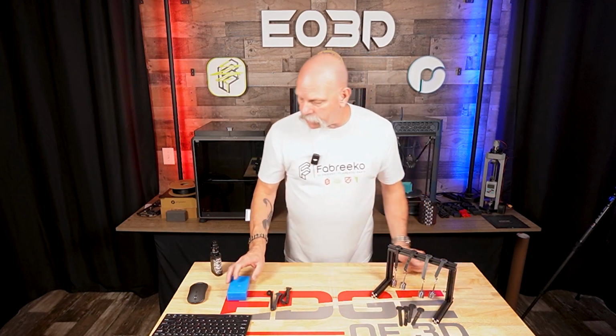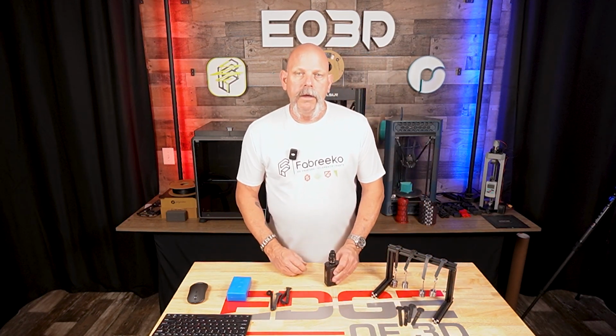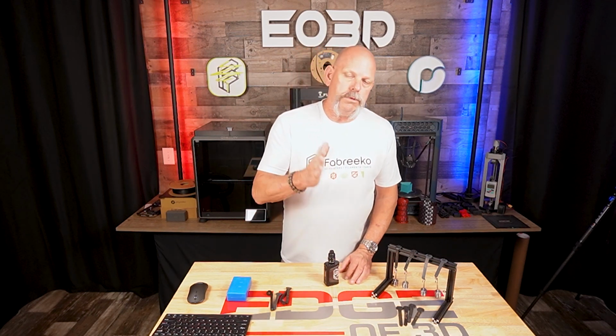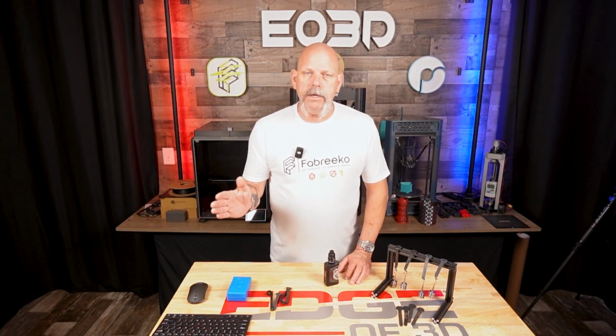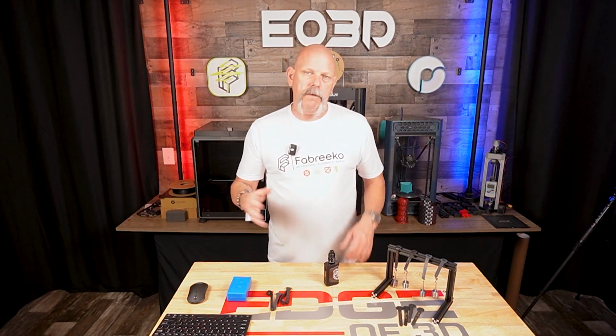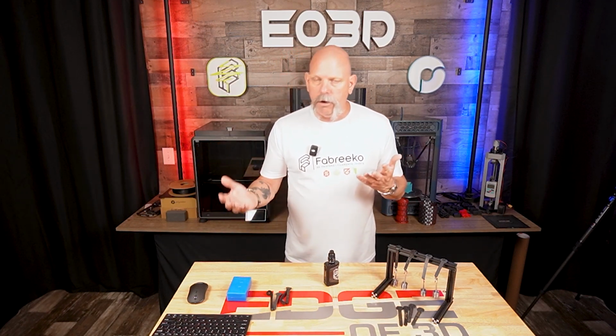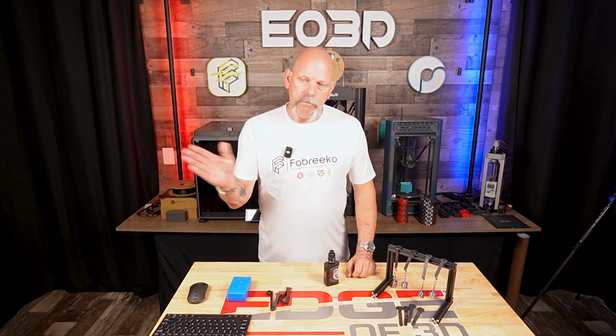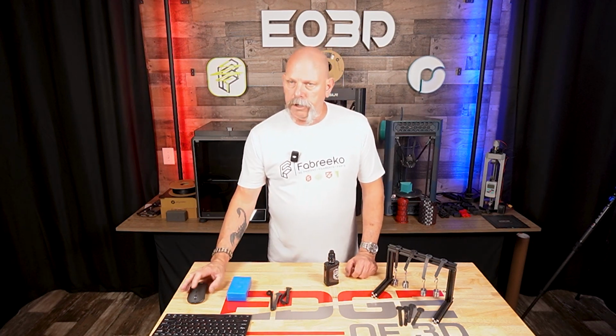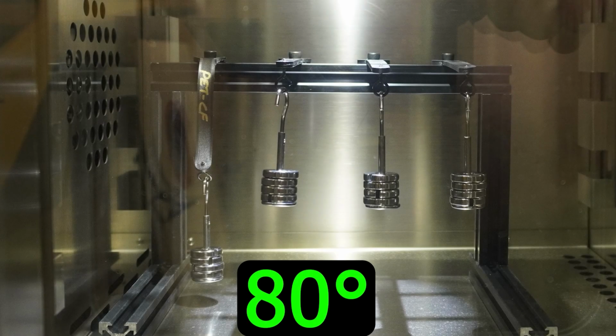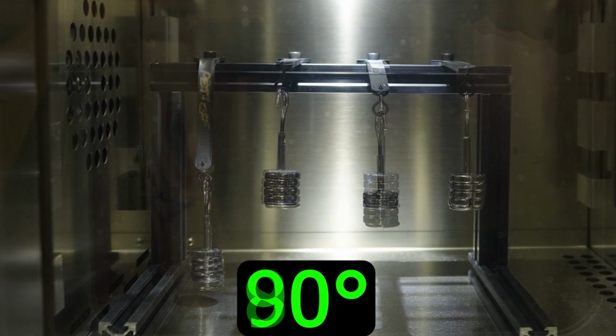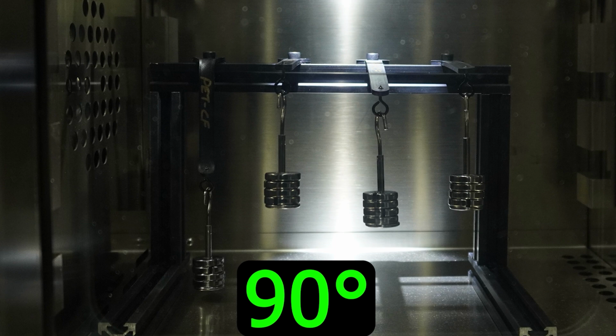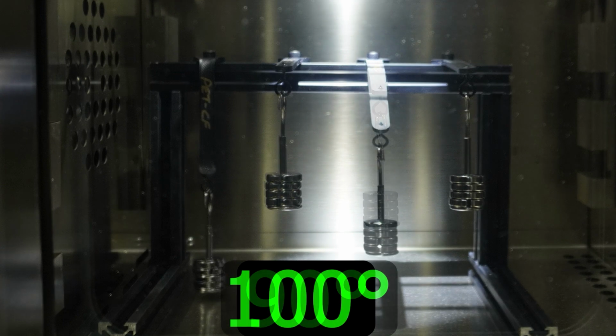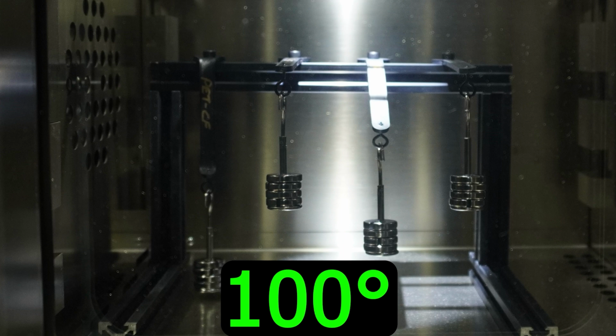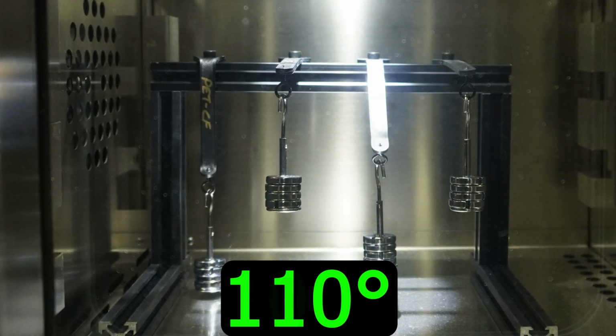But we'll jump into a time lapse here, and I actually did it every 5 degrees, but for the sake of time and video, I only put every 10 degrees in the video. But you know, we'll start off here. That's at 80 degrees. The PET carbon fiber that wasn't annealed failed immediately. At 90 degrees, you can see the PPS is starting to sag quite a bit.